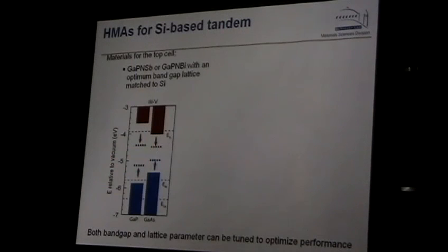However, we could use again our manipulation of the band edges. In this case, it would be gallium phosphide nitride with antimony. Nitrogen pushes the conduction band down, and the antimony pushes the valence band up. So we can make gallium phosphide lattice matched to silicon, because it's already so close to silicon. It could be lattice matched and with the proper energy gap.